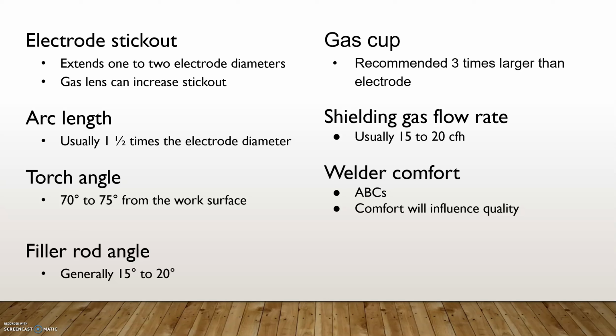Page 11 and 12, electrode stick out extends 1 to 2 electrode diameters. Gas lens can increase your stick out to get more gas coverage. Your arc length is usually 1.5 times the electrode diameter. Torch angle is recommended 70 to 75 degrees from the work surface. Filler rod angle is generally 15 to 20 degrees.